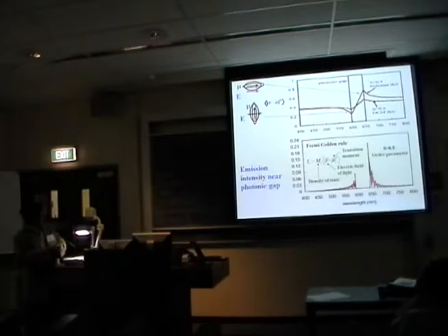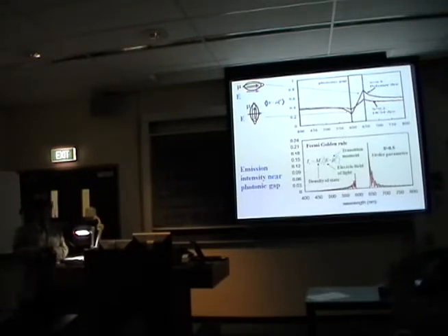However, at the higher energy edge, the dipole and electric field eigenmodes are perpendicular to each other. So this gives a minimum. And this difference is larger if the system has a higher order parameter. If the molecule is perfectly aligned, then this must be much, much larger.